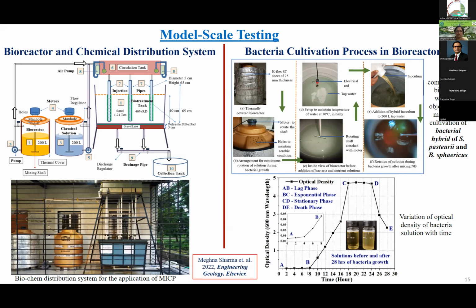Up to 0 to 8 hours, the growth was quite slow. It was working around slowly. That is called the lag phase in bacterial growth. After that it increased rapidly. That is the exponential phase of bacterial growth, from 8 to 16 or 18 hours. Then the stationary phase occurred, meaning the growth and death of bacteria became similar. After that the death phase increases, as the bacteria's optical density gets reduced. So these are the four major phases of bacteria which are generally observed.